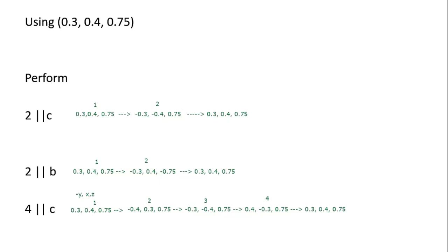It's very important that for a fourfold rotation, you remember this operator. This is very important. So for a fourfold rotation, you're always going to be doing this operation. Now for a twofold parallel to C, if you're curious about that, the operator is negative x, negative y, z.